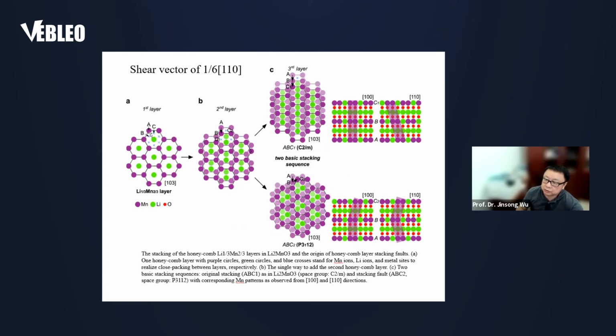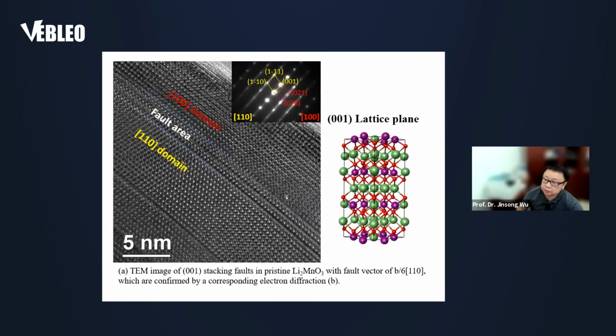From A to B to C, or from A to C1 to C2, there are several possible positions for the atoms in the layers to occupy. So this is the sample that we use to do the delithiation. This is the LMO sample, and in the pristine sample, they are not perfect single crystals. They actually have different domains. We have 100 domain, we have 110 domain, and also a lot of faulted area full of defects.